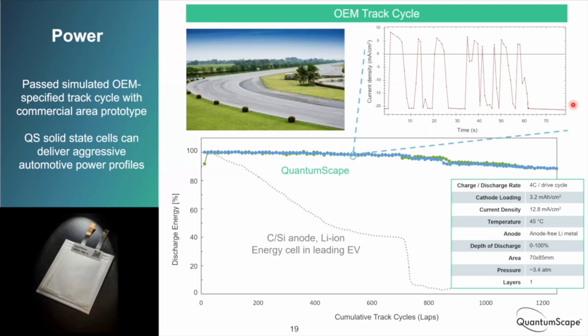And then we repeat to get to about 9 or 10 laps around the track until the battery is fully depleted. And then we go into a 4C fast charge. Then we just repeat that cycle of laps around the track until the battery is fully depleted and 4C fast charge, continuously. This graph shows two of our cells and how they perform on that test, showing pretty gradual fade over 1200 laps around this track. This test is quite stringent. If you put a leading energy cell that came from a leading automotive company on the same test, it fades much more quickly, just because this is a very aggressive test. And again, for all the test conditions listed here, this was done on the same generations of cells that I've been describing in the last few slides.